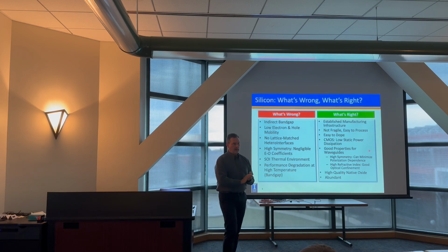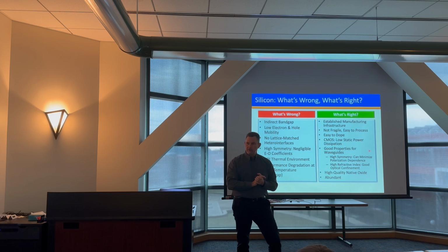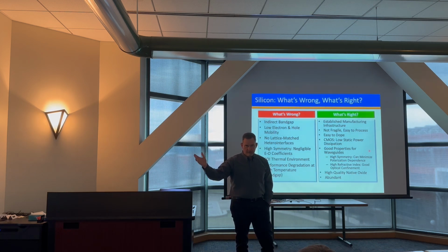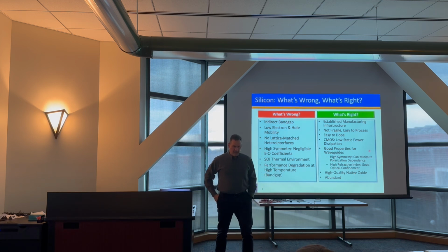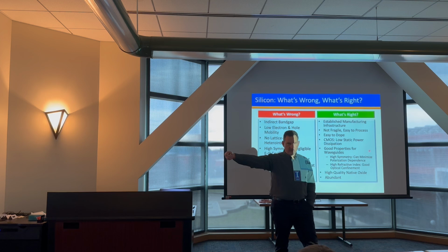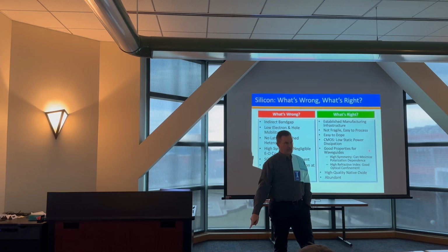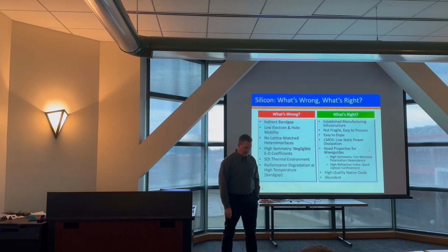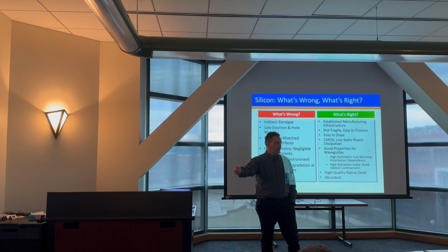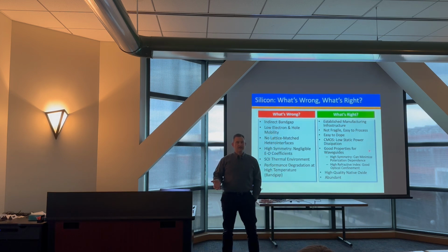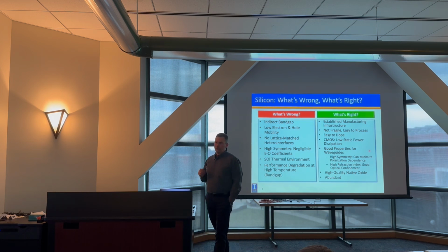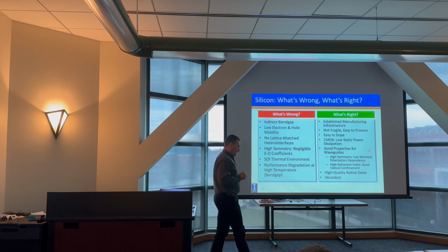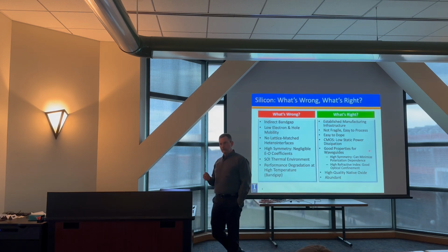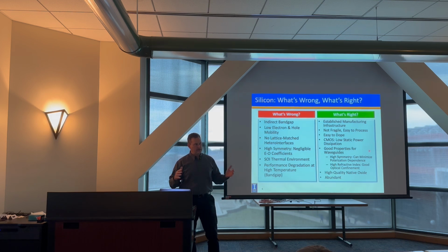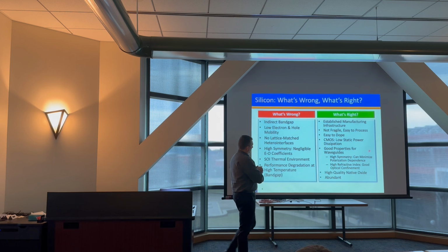Silicon is robust. If you work with silicon versus 3-5 materials, and how many of you handle 3-5s regularly? Probably at least a handful of you. If I have a silicon wafer and I'm holding it with tweezers and I drop it from here, it's probably going to bounce. Maybe it'll break, but it'll probably bounce. If I do the same thing with gallium arsenide, it's going to break. If I do the same thing with indium phosphide, it's going to break even worse. The fragility of the compound semiconductors is difficult to deal with when you talk about scaling up your processes, and that's one among many reasons why you haven't seen the same scaling in 3-5s as you've seen in silicon. It's easy to dope, different types, P-type, N-type.